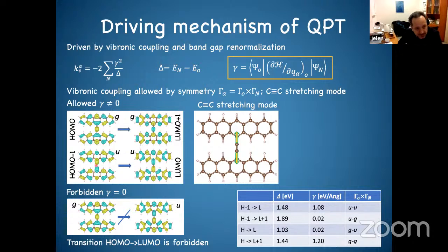This is not zero. And this also, because both are ungerade, they have the same symmetry, so this couples to this one. But if I have two states here, occupied and unoccupied, which have different symmetry, this vibronic coupling is zero. Okay, so that I can calculate it. I calculate it, and you see here that if I have a transition between two orbitals of the same symmetry for this vibration, there will be some coupling. But if they are different, this will be zero.